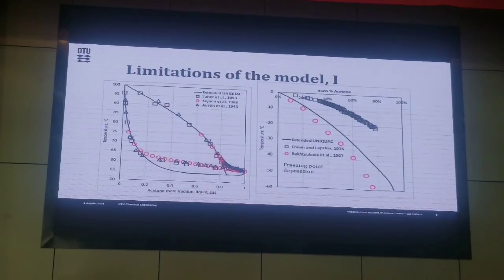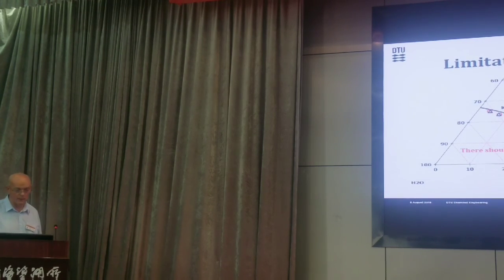But then in another study where they did dielectric relaxation spectroscopy, they actually claimed that the temperatures and compositions corresponding to the red ones are freezing points and that could be melting points that correspond to the black ones here. And that actually is not pure ice that is freezing, but actually it is a hydrate, acetone with 17 water molecules. So that is something that complicates the system, that basic data like freezing points are not unanimous. You cannot be sure about what it means.